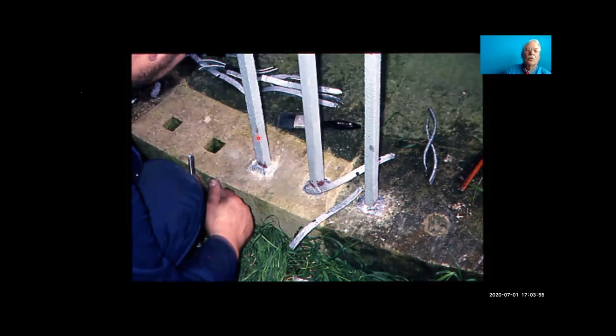So the lead is poured in round the paling, but it must overfill the hole so that you then dress it down so that it's nice and watertight. Otherwise, there's a little bit of a gap where the lead contracts away from the metal. Okay, important not to just use resin where we have these traditional fastenings.